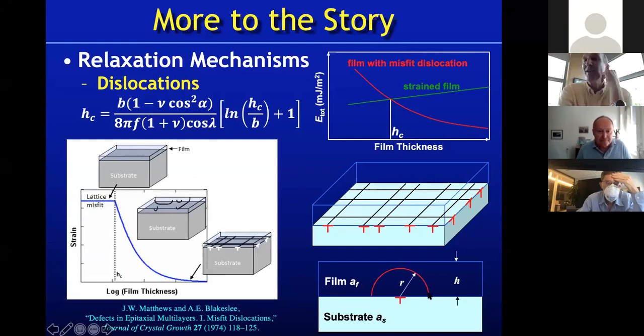Okay, so the idea is it costs energy to strain the film. So if you are just putting your dislocations at the surface of the film, yes, you can relieve the strain above that point, but only by pushing the dislocations down to the interface do you relieve the strain of the entire film, which is what's adding up to give you this big strain energy. Now, dislocations can be hard to move. We're dealing with nice brittle materials, so glide may not be possible in this material. So maybe it's going to crack. But anyway, they would like to make their way down to the interface.